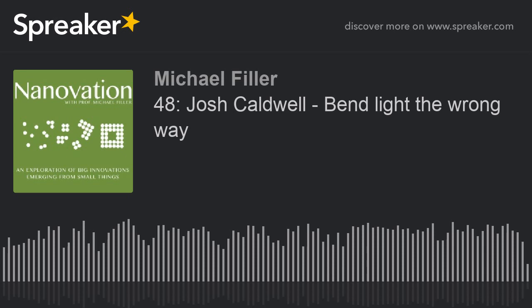And then with a paper from Thomas Ebbesen's group in the late 90s, they observed within a thin metal film with periodic arrangements of holes that the transmission of light through those holes was such that you'd actually get more light through than you'd predict based off the open area. Think if you had a window with wood pilings on it, and you shone light through it, and somehow you got more light through because the light never was absorbed or reflected off of the wood. It was like all of it got through. And so in this case, it turns out that these surface plasmons were actually providing a collection and a funneling effect through those holes so that it would open up the absorption cross-section or the collection efficiency of those holes and therefore allow more light through.